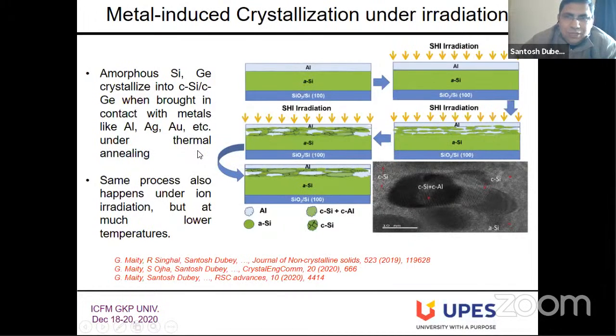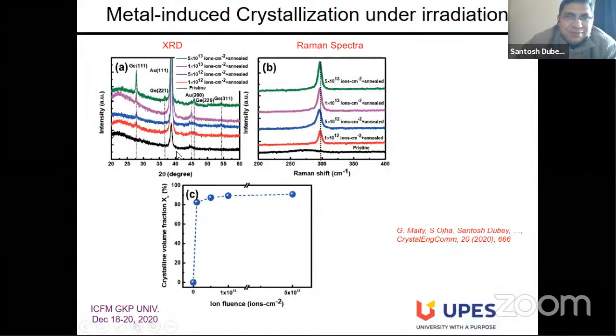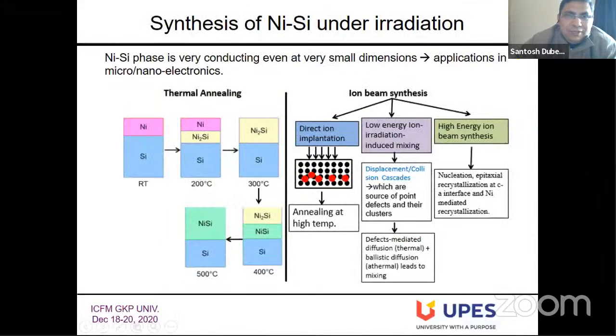I won't go into detail because of the time. One thing I'm working on, which is very new, is under review with Thin Solid Films: synthesis of nickel silicide. Nickel and silicon has a very complicated phase diagram, but nickel monosilicide is very, very conducting. When you reduce the length scale or the size of nickel silicide, it forms nickel monosilicide, which is very conducting.